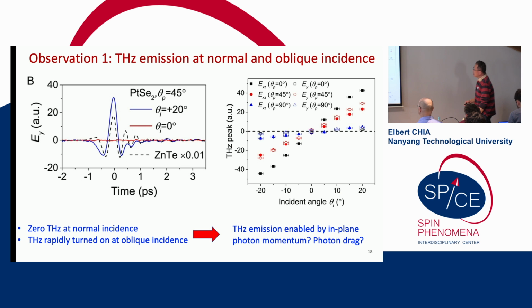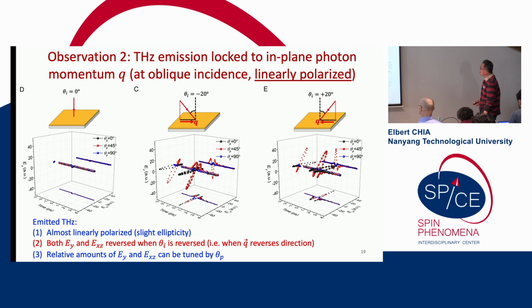So observation one, we pump at normal incidence. We don't get anything, which is what we expected. And when we pump at oblique incidence, the Terahertz is rapidly turned on. And then when we change the incident angle, you can see here for small angles, it is roughly linear. And so this observation tells us that perhaps the Terahertz emission is enabled by the photon momentum, which suggests that this Terahertz emission mechanism is photon drag.